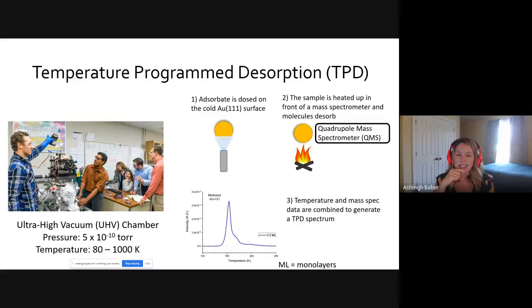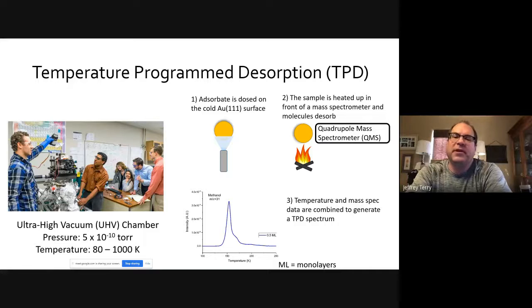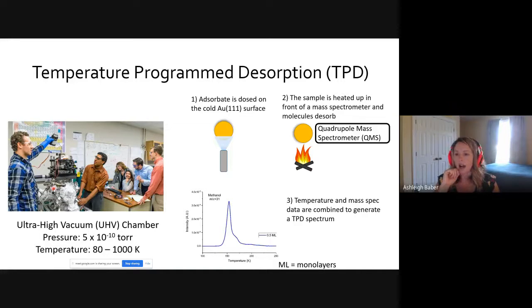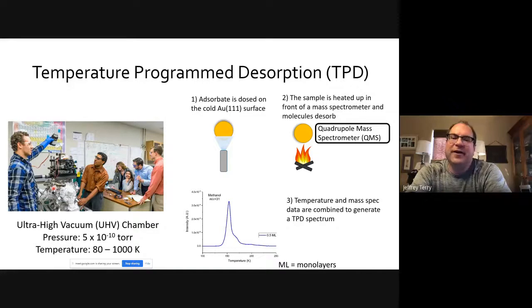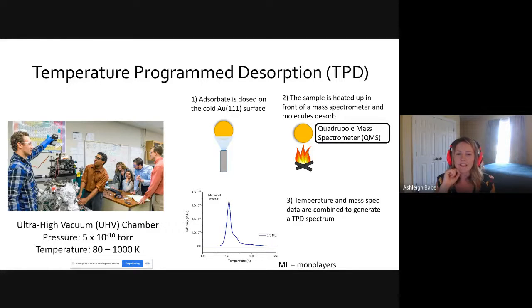After we deposit it in oxygen, we run an annealing cycle. We keep the oxygen present to make sure that these titania particles get fully oxidized. So are we talking torr, millitorr? Oh, no, 10⁻⁶ torr? 5 × 10⁻⁷ torr of oxygen. For about, we'll make sure that first oxidation cycle is about 30 minutes.